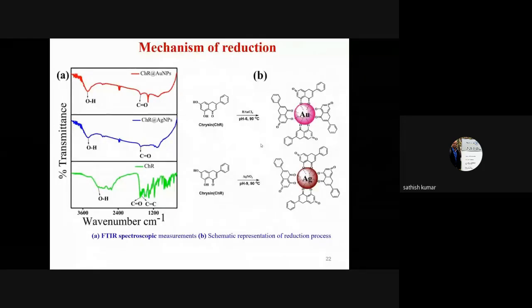Here, as compared to the free chrysin molecule, the chrysin that is functionalized with the nanoparticle shows the involvement of hydroxyl and carbonyl group. So an electron from the hydroxyl group of the chrysin is donated to the Ag+ or Au3+ ions, which convert them into Ag0 or Au0, and the carbonyl group will be in a coordinated linkage with the nanoparticle. So the quinone form of the chrysin is functionalized on the surface of the nanoparticles. So this is the important thing about the polyphenol based nanoparticle.